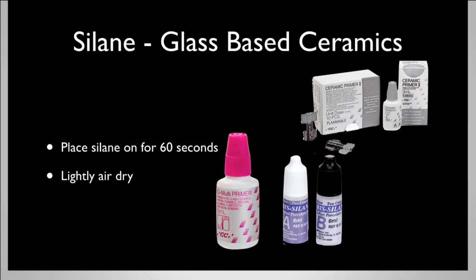Now, once the restoration is etched, and that normally happens in the laboratory, but if you're doing it in your own office, the next stage would be silanation. So we get the restoration back from our ceramist pre-etched, or we etch it in our office. We then want to silanate, and we want to place the silane on for about 60 seconds. That allows the ceramic chemistry to respond to resin. It's essentially a coupling agent between ceramic and resin.